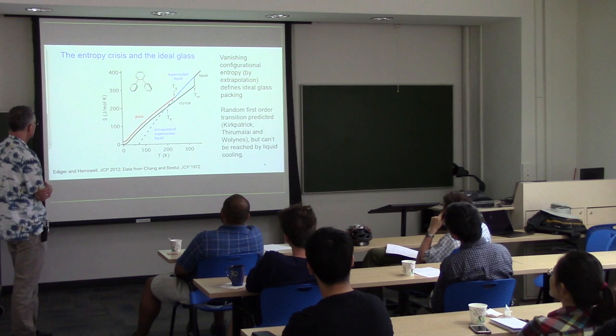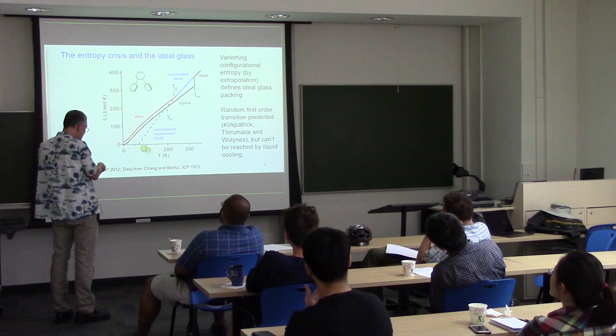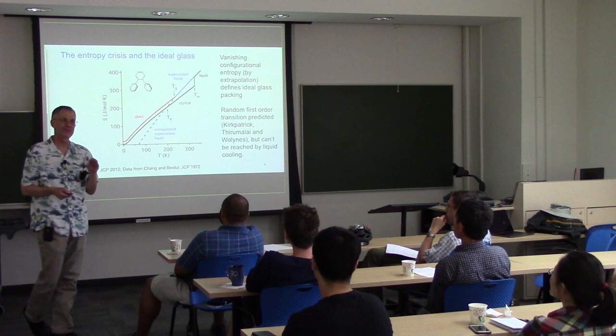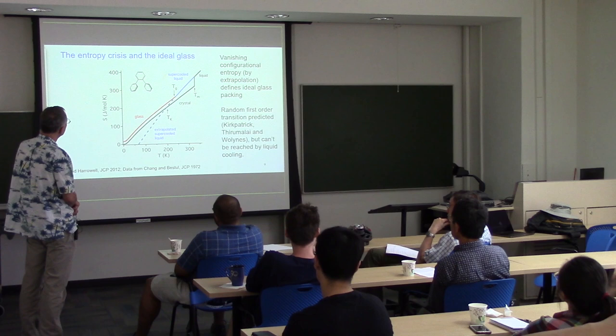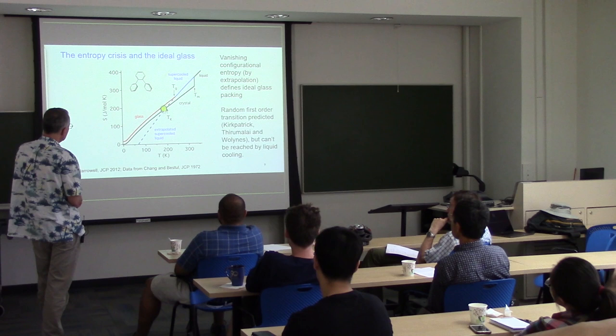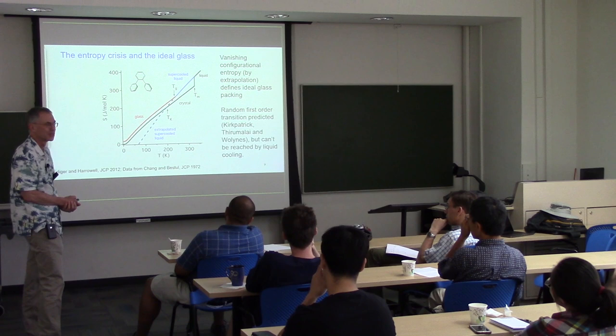And so this part right there should alarm you. The part where the extrapolated entropy goes negative and would be negative at absolute zero, okay? So for most formulations of the third law, this is a violation of the third law. And probably we really have trouble way, way up here, where the entropy of the supercooled liquid goes below the entropy of the crystal.